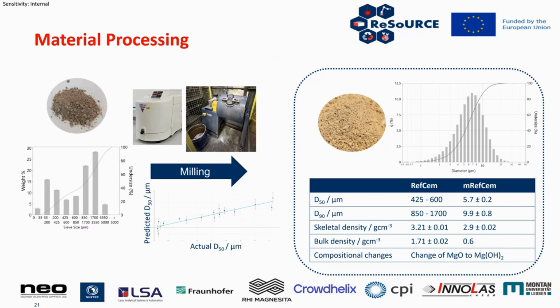We first began in the lab on a benchtop scale with about 10 grams of material, using a planetary ball mill to reduce this to below 10 micrometers in size. We're using an adaptive DOE software to guide our optimization of this process. And then we upscaled this to a multi-kilogram size process, milling this material. And we can see that we changed this material. So we reduced the D50 to below 10 micrometers. The D90 is also below 10 micrometers.